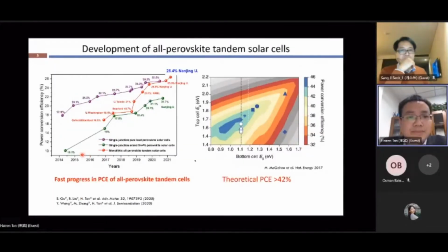And in the past 4 years, mainly due to the very fast efficiency progress of narrow bandgap perovskite solar cells, the progress of all-perovskite tandem devices has also been very fast. Currently, the highest certified efficiency, recently obtained by our group, is 28.4%. This efficiency is already higher than the best performing single junction perovskite solar cells obtained by the group of Professor Sok. But still, we know that the theoretical efficiency of tandem devices is about 40%, and we still have much room to improve the efficiency for these tandem devices.